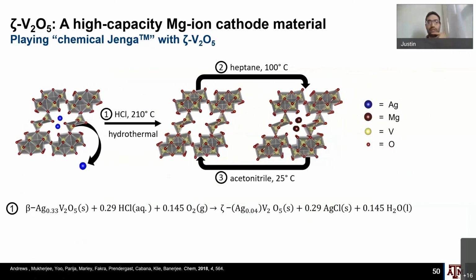And so what we initially did was just do topochemistry. We were able to reversibly intercalate magnesium into the structure and then pull it back out to show that magnesium actually is going into the structure. This is actually a very difficult thing to do. I should have mentioned that before, but lithium ion diffusion is much easier because it's a monovalent ion. There's only one polaron, one electron that's moving with the lithium through the lattice. But in the case of magnesium, you have a divalent ion and also two polarons that form in these very insulating materials.